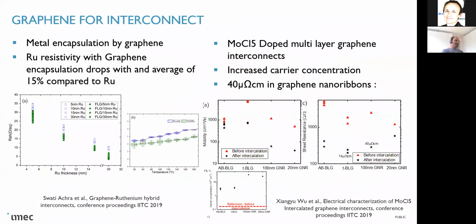This could be emerging slightly earlier than foreseen, but the combination of graphene with interconnect metals seems to have some promise towards improvement of the resistance of the wires. This is an exercise that was done at Imec by Swati, where you can see that by combining ruthenium with graphene, you have basically a lowering of 15% of the resistance of your ruthenium wires compared to without graphene. There are also multi-layer interconnects, and we also did some work at Imec in trying to find out if there is a way to be competitive or even better to outperform copper.